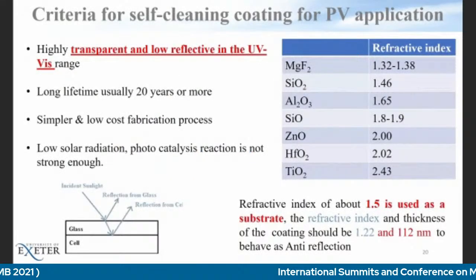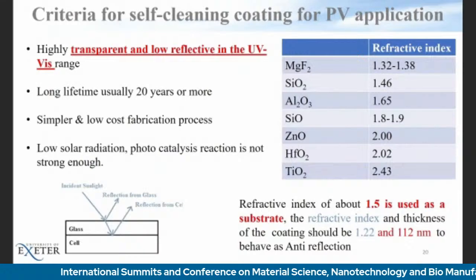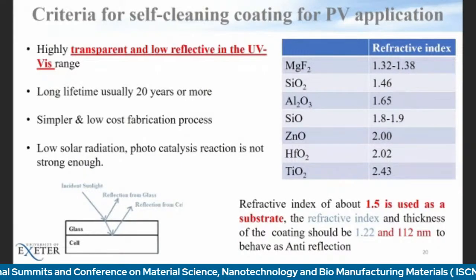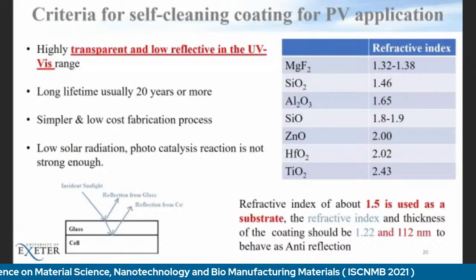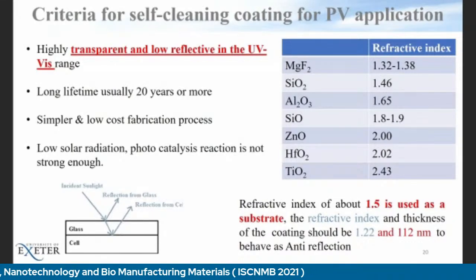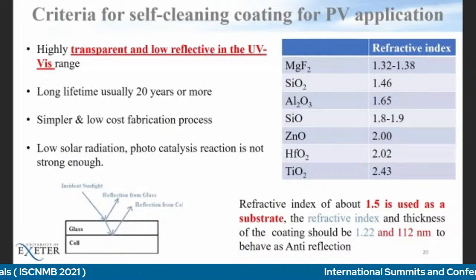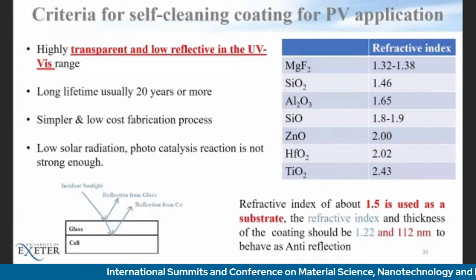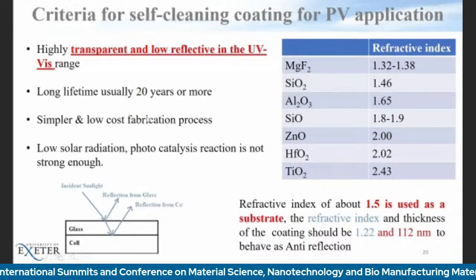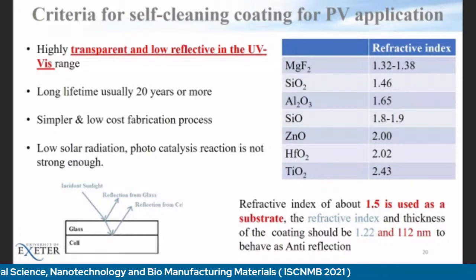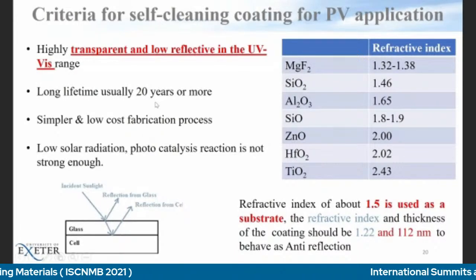But the challenge with self-cleaning with hydrophobic or hydrophilic, particularly for solar application, is that we have to make it very transparent and with a low reflective index, because for solar, transmission is a major issue. If you don't have enough transparency on top of the glass, your solar cells will not get enough solar radiation, and that means you will not generate that much power. Also, our target is to employ solar cells or photovoltaics for at least 20 years, which means your coating has to be active for at least 20 years.